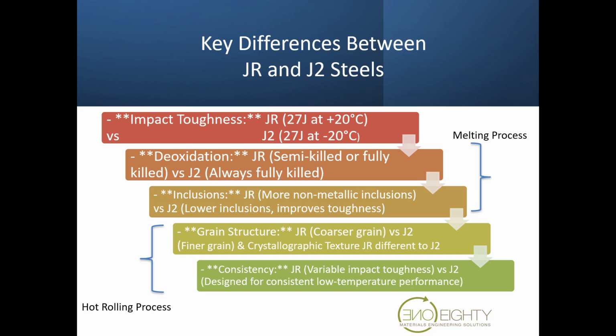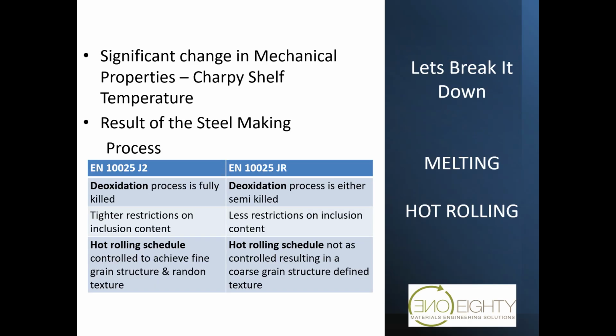With the hot rolling process, the grain structure, JR has coarser grains compared to J2, and JR has what we call crystallographic texture, which I'm going to explain in detail, which is different to J2 material. And that is tied up in how the material is hot rolled, the temperature at which it is hot rolled, the speed at which it is hot rolled, and how much reduction in gauge is applied to the steel as it goes through each pass during hot rolling. So there's a very different recipe in hot rolling schedule, that's what it's called, for JR material compared to J2 material. And there's a very different way in which deoxidation and inclusion control is managed for JR and J2 material.